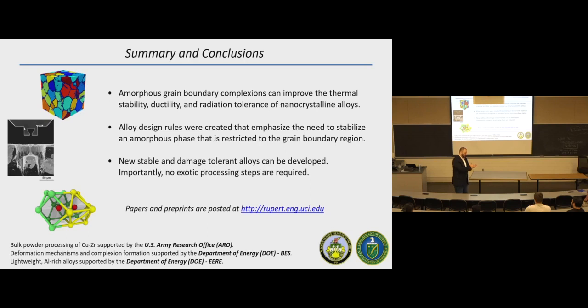But the way we're going to do this is we're going to deposit these layers and make them with a little bit more controlled grain boundary composition, a grain boundary composition we know is there, then heat it up to close to the melting point. And then in that case you're able to compare apples to apples. So it's a good question. I don't have the answer for you right now, but in a few months maybe I will be able to tell you. It certainly will. There will be an optimal grain boundary composition for forming the glass. That's true.